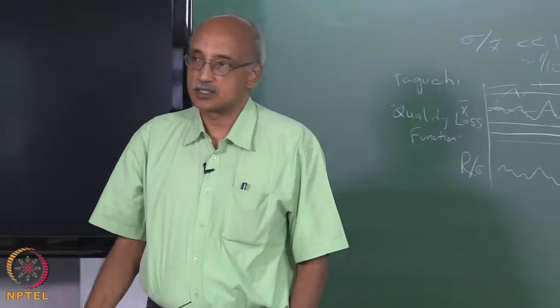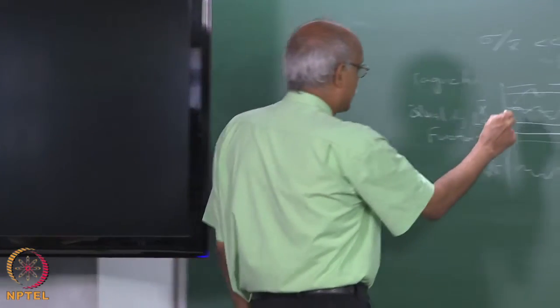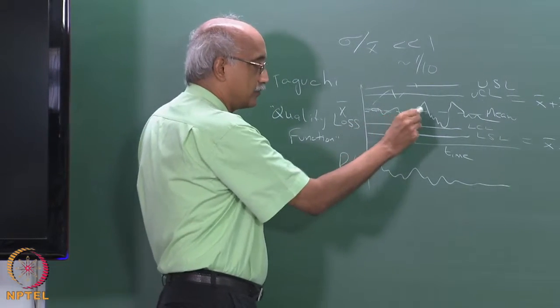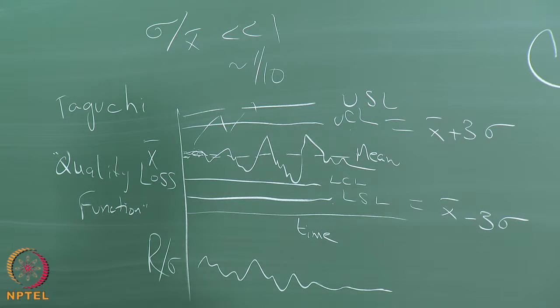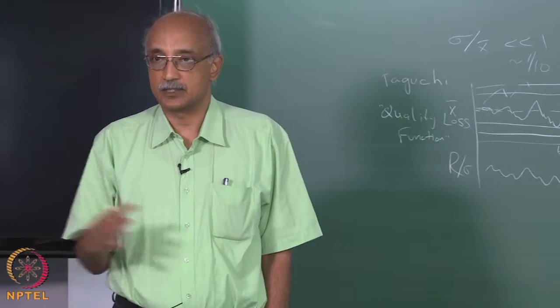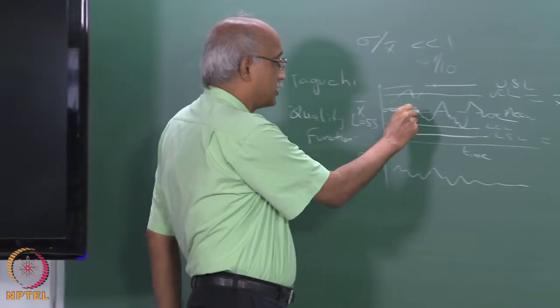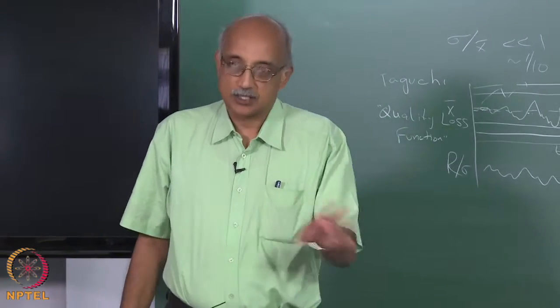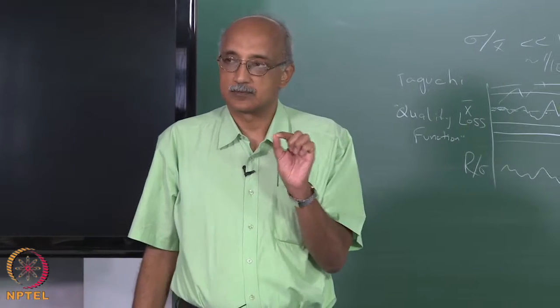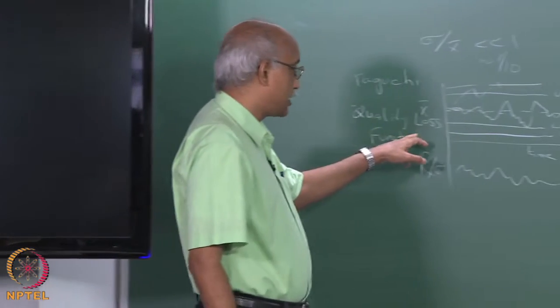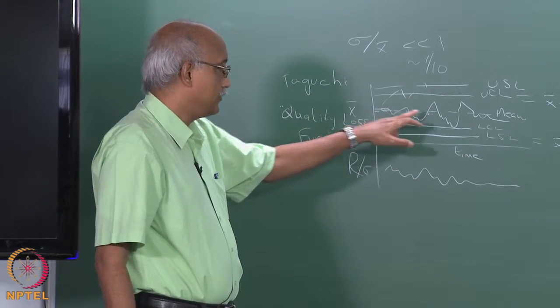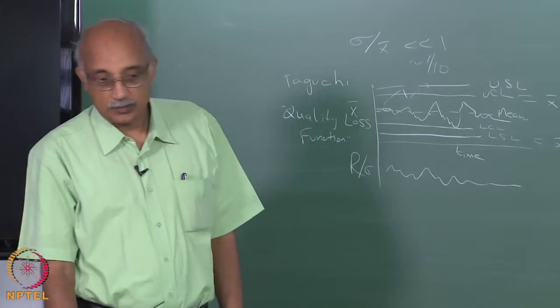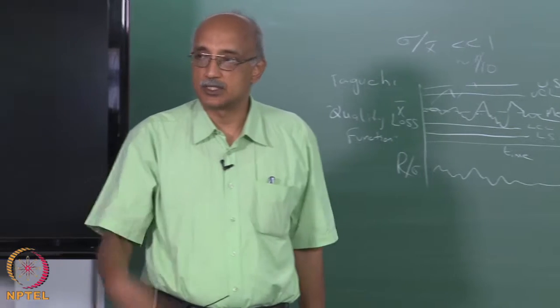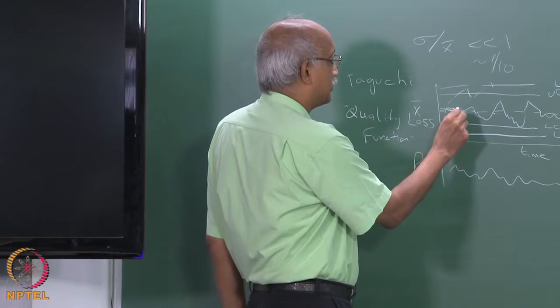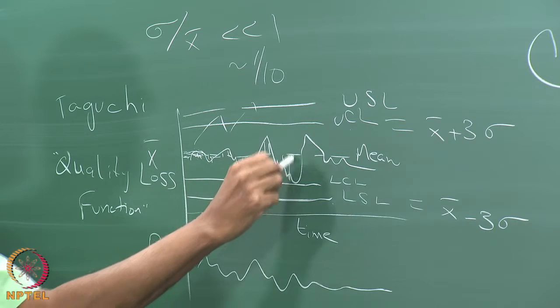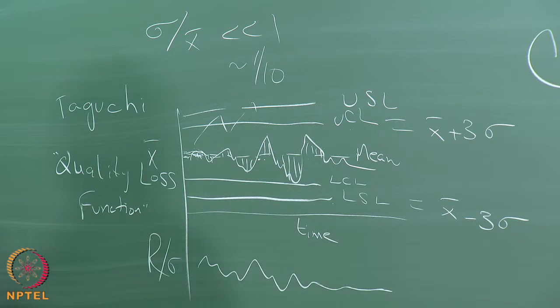Taguchi was a famous engineer, statistician, who said that any time the product measurement deviates from the mean or its ideal value, there's a loss associated with it because the product is not as good as it can be. So he says anytime you see any deviation from the mean value, treat it as a loss, add up the losses and try to minimize that. So what he defines as quality loss function is the summation of all deviations from the process mean, and he says in a good process that should be 0, or you should try to drive it to 0. In other words, if you integrate and find the area between the trend line and the mean line, that integral should be driven to 0 in your process.